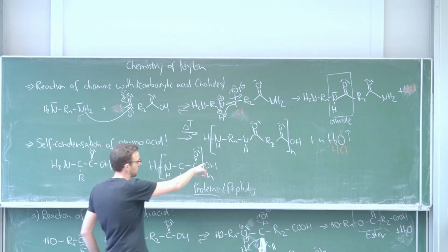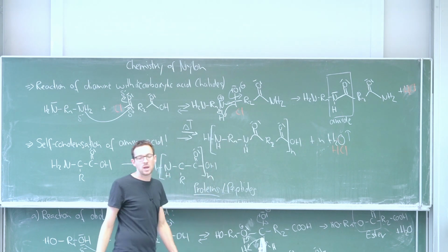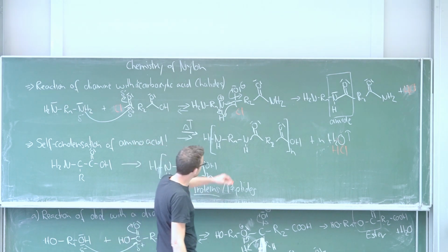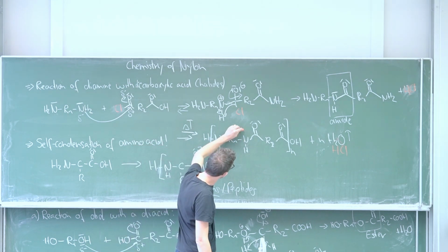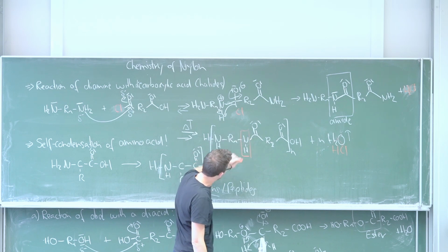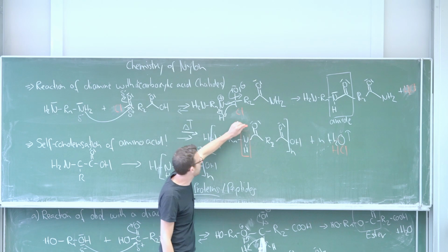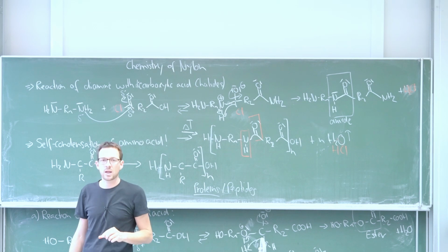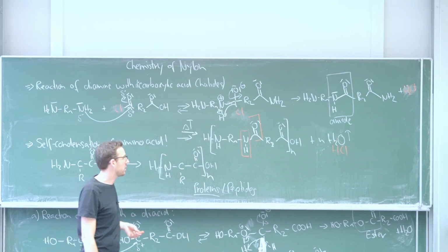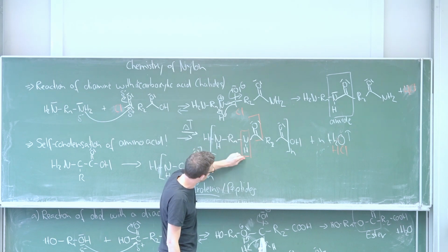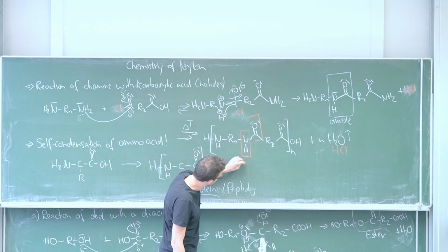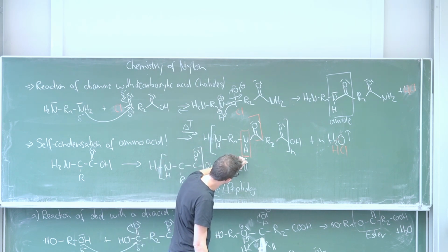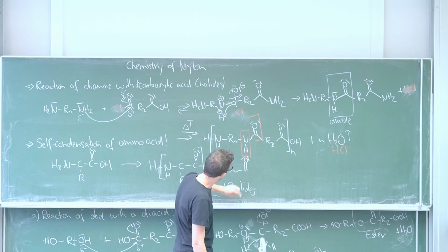And now we can directly see, if we, for example, take this polymer here, why nylon is so effective, or polyamides are so effective in doing this. Now you can see we always have an NH in the neighborhood of a C double bond O, and both of these groups can undergo hydrogen bonding with each other. So every time we have this in the vicinity, we can have the next polymer. Hydrogen bonding.